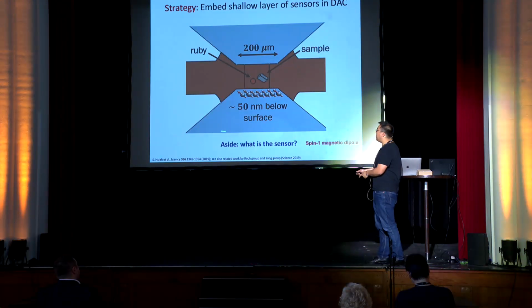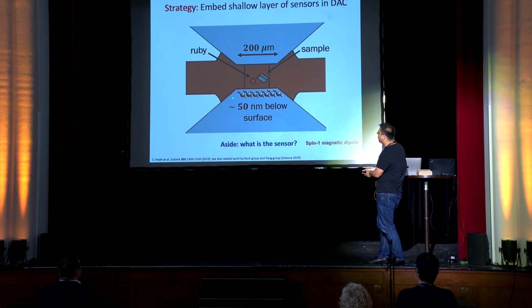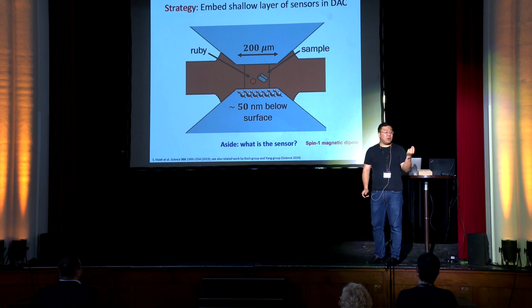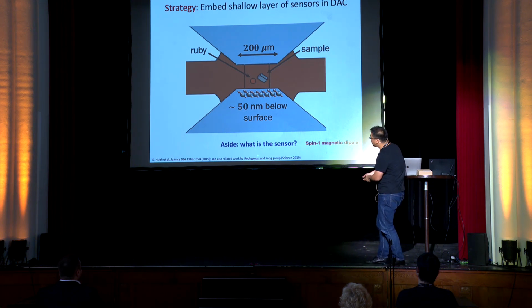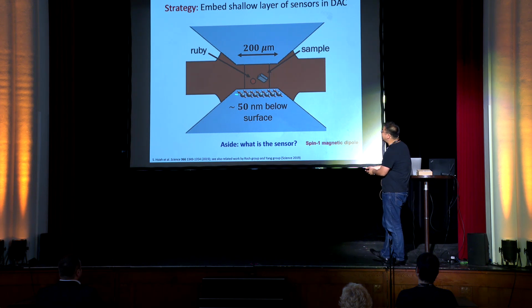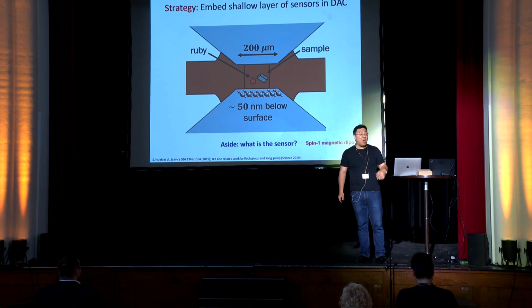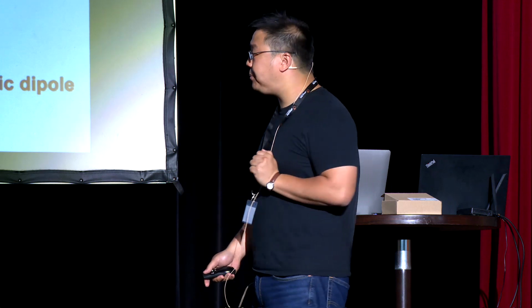And then the super simple idea is to do, for example, confocal microscopy, assuming that one can transduce the magnetic signal that's measured by these sensors into an optical signal. Then one can do confocal microscopy through relatively transparent diamond and image exactly what the magnetic field measured by these sensors is, locally. And because they themselves are close to the sample, one gets to make local pictures, take images of magnetism inside the sample chamber as one is applying pressure. So a very, very simple idea.